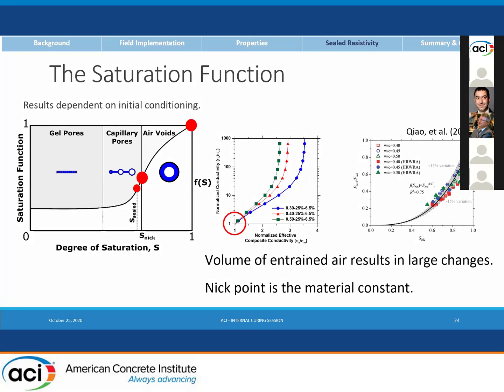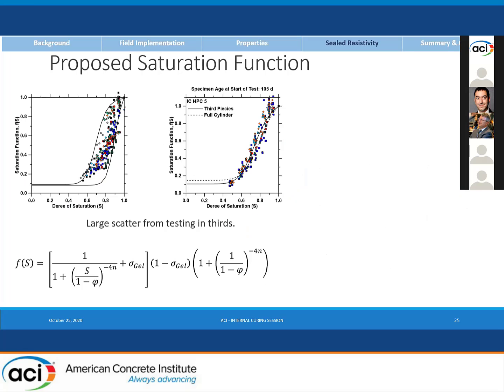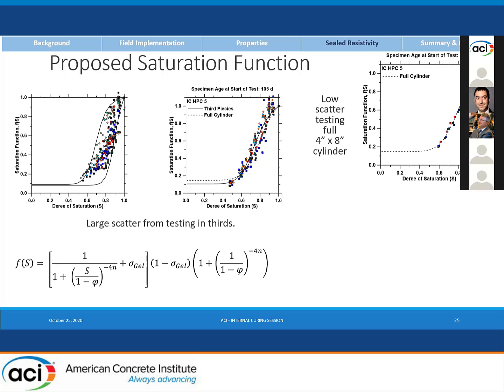Qiao went back and last year they came out with some actual data to suggest that indeed that's what they find. So this is the saturation function that I am recommending or proposing here. It's got a lot of jazz going on, but it's essentially treating those three different contributions together. I also recommend that we not chop cylinders into small pieces, because you start measuring the void distribution throughout the height of the specimens. And so it turns out if you just do it on the full 4x8, you get exactly what you're looking for.